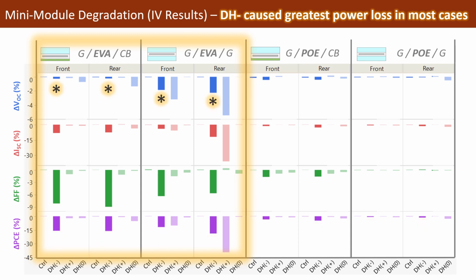Interestingly, for the glass-glass EVA samples, we also saw VOC loss under the negative bias damp heat in addition to that typical shunting mechanism. I'll show you this later in the imaging, but we attribute this additional VOC loss to a backside polarization effect that decreases the passivation quality.